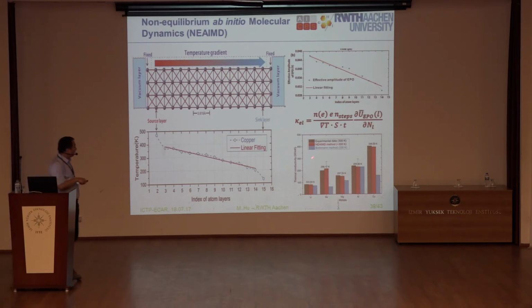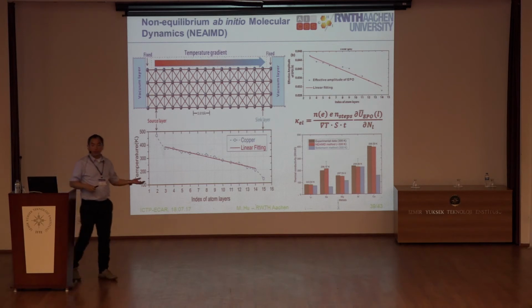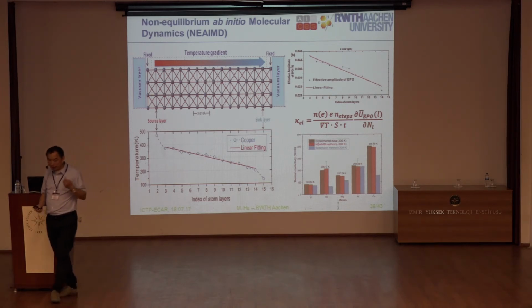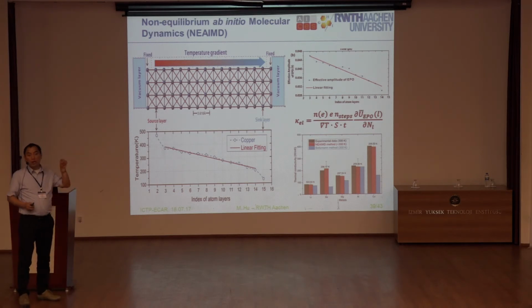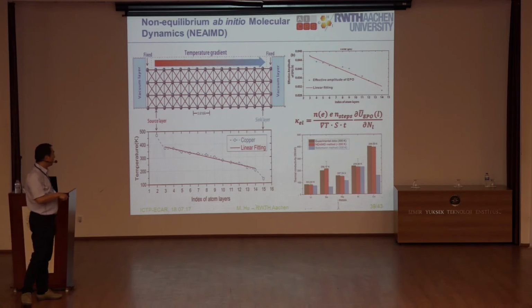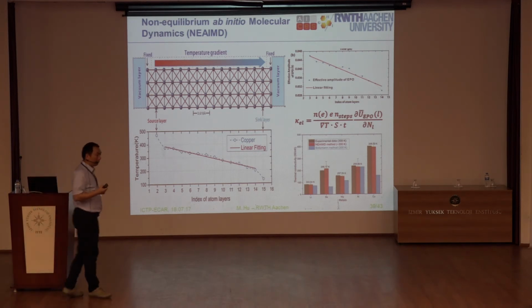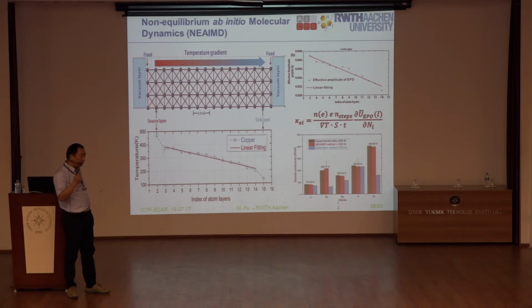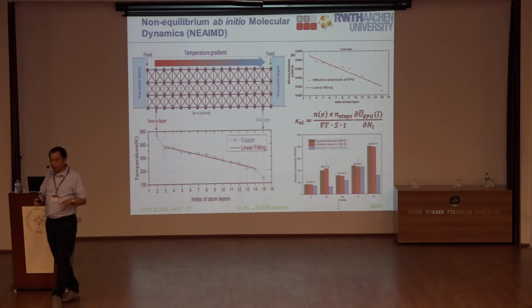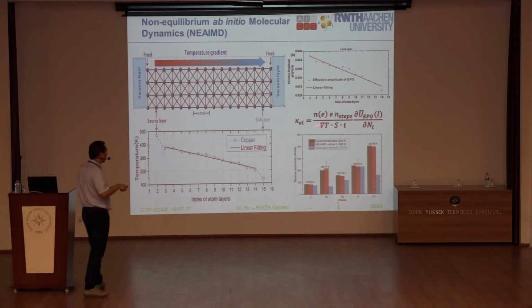And also you can compare with this blue one, which is the BTE model. So this is the electron gas model. As I just mentioned, in the classical electron gas model, there's a critical parameter, this tau, the relaxation time of electrons. You don't know, right? Then we just typically choose like 10 femtoseconds, which is very typical in experiments or in literature. And then you can find that the BTE or the electron gas model can predict thermal conductivity very well for some materials, but some materials cannot, right? For example, copper and this Be metal. And then if you choose this relaxation time as 10 femtoseconds, you can find a significant difference, right? But our model does not involve such a parameter. We do not need this value. So we can directly calculate electronic thermal conductivity for the pure metals.